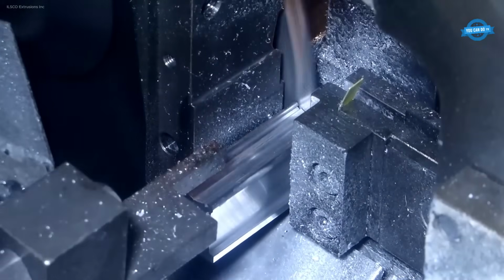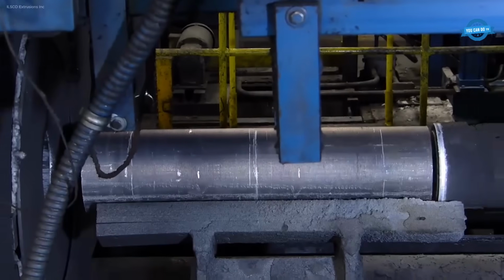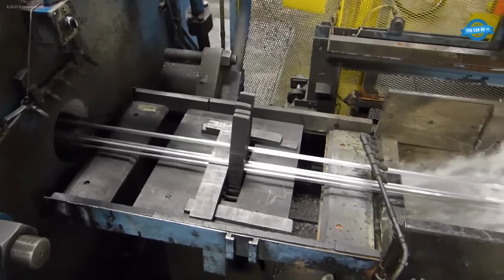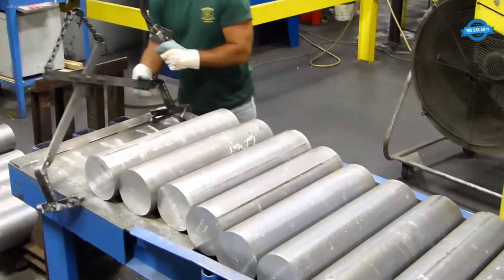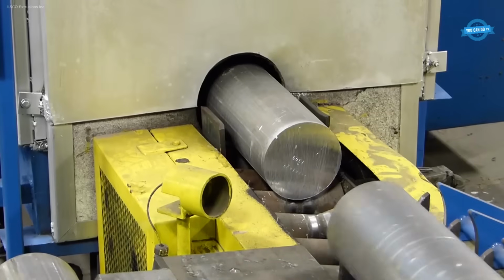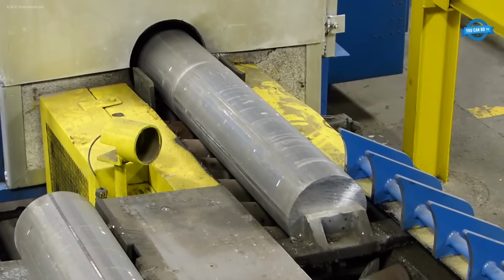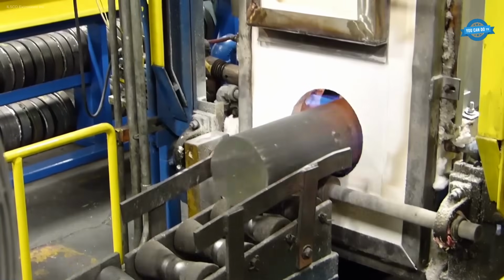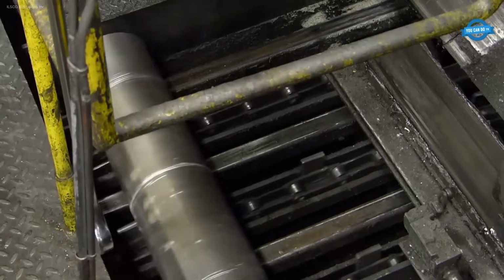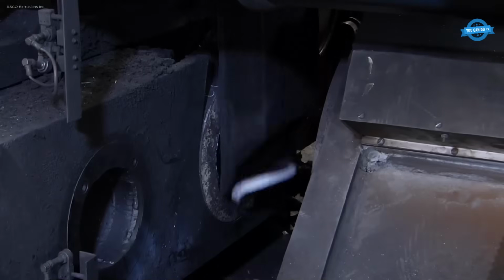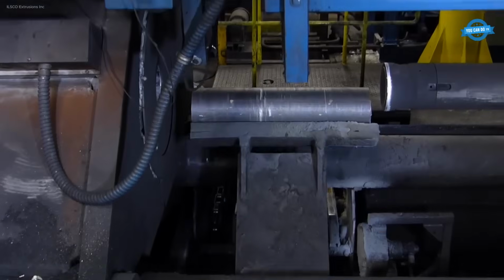When solid aluminum transforms under intense pressure and heat, you get something extraordinary. Precision-shaped profiles made for real-world performance. The process starts with aluminum logs cut into uniform billets, then heated to around 900 degrees Fahrenheit in a billet furnace. This softens the metal without melting it. Next, the billet is pushed by a hydraulic ram through a preheated steel die, creating the desired profile in one powerful stroke.